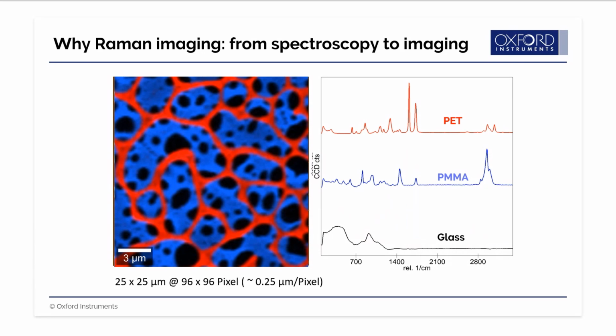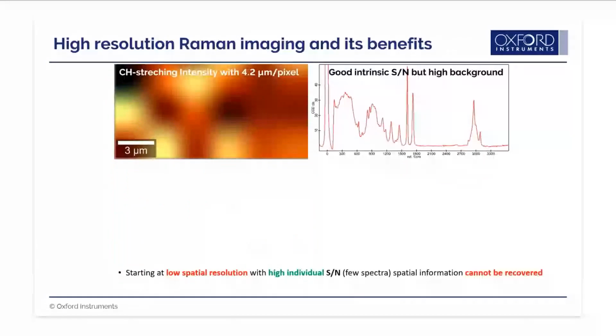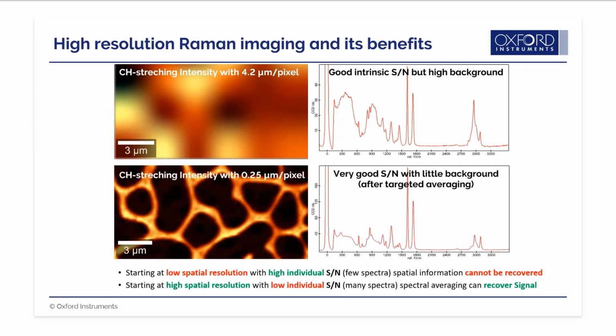The take-home message here is, if you start with low spatial resolution but high signal-to-noise few spectra, the spatial information cannot be reconstructed. On the other hand, starting at high spatial resolution with low signal-to-noise individual spectra, spectral averaging can recover the good Raman spectra.